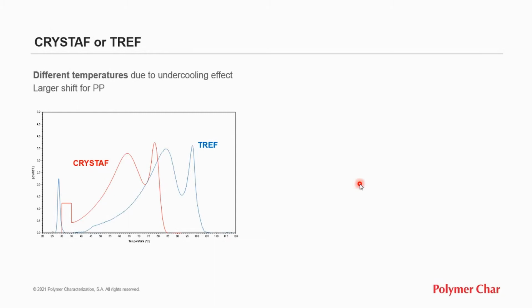Okay, so CRYSTAF and TREF are crystallization techniques, both working in dilute polymer solutions. As we can see in this figure, for the analysis of the same material, polyethylene in this case, by CRYSTAF and TREF, both techniques provide equivalent results for the chemical composition distribution. CRYSTAF is run in a vessel with no support and measures the cooling cycle during the crystallization of the polymer, while TREF is run in a column and data is obtained during the heating, the redissolution. Due to the polymer undercooling effect, this causes differences in the observed temperatures.